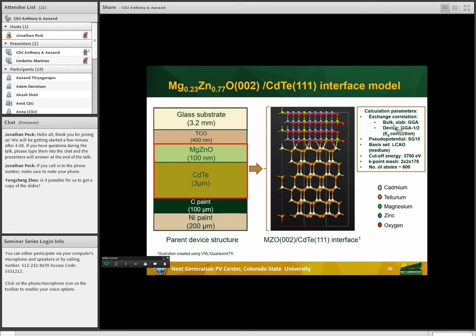We used an SG15 pseudopotential within the generalized gradient approximation functional for the bulk and interface. Whereas for the device calculations, we used a semi-empirical method to obtain accurate band gaps.